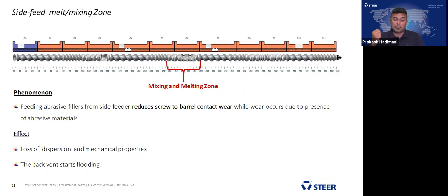What is the effect? Loss of dispersion, because wear and tear takes place. Due to that, there is loss of dispersion and loss of mechanical properties. The back venting starts flooding. That again blocks and reduces the final throughput.